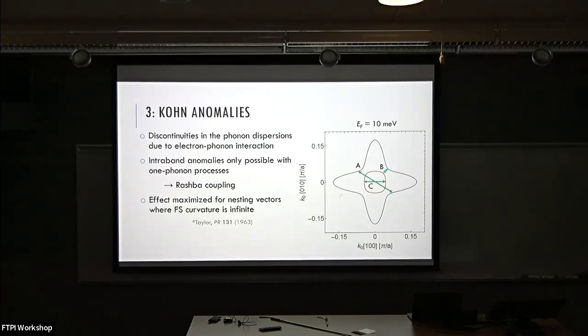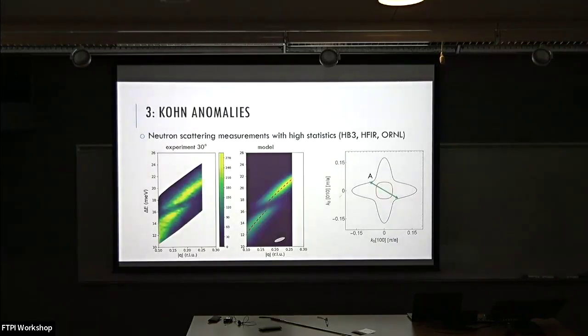But of course, there's other nesting vectors, and we can try to do neutron scattering and see if these anomalies are there. And so we did neutron scattering measurements with very high statistics. This was a huge sample, and we counted for quite a long time. So we have really nice data. However, it turns out that we didn't really need to do that. So one of these anomalies, this A, is actually huge.